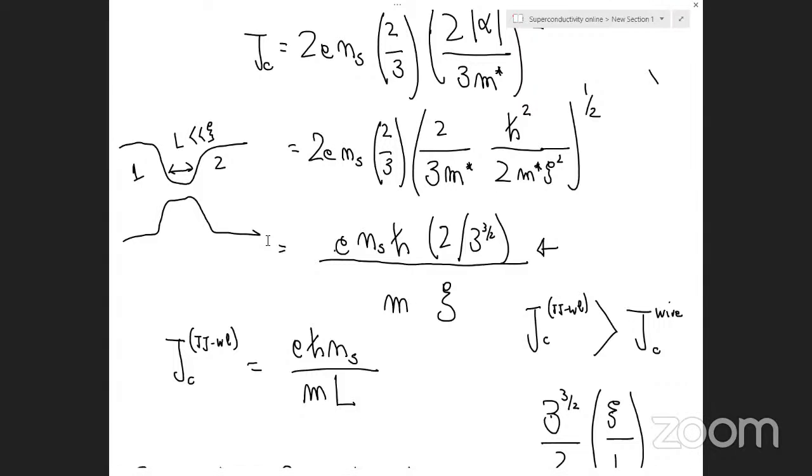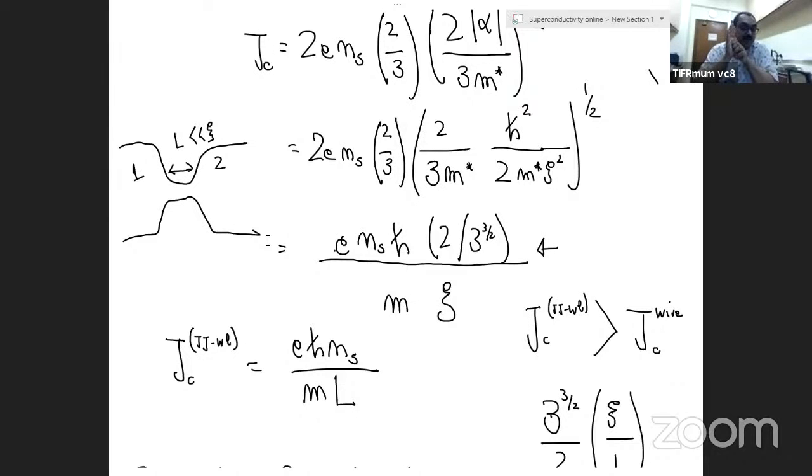The prefactor of h-bar v_F. Exactly. But that doesn't matter, because the coherence length you estimate from any experiment is not very precise. It's precise only within a factor of the order of unity. So for any physical phenomena, the exact value of the BCS coherence length is not of any particular significance. All right? Okay, sir.